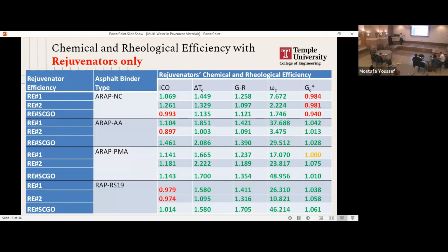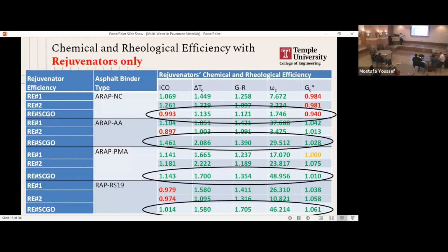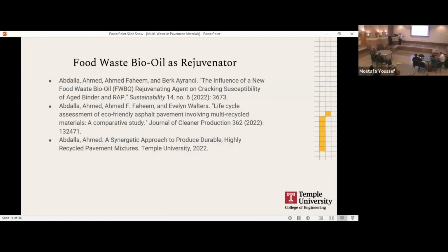These are the different rejuvenators, evaluated through changes in fundamental rheological properties, frequency, crossover modulus, through the improvement in thermal relaxation with the delta Tc, through even improvement in the chemistry with the FTIR measurement. And again, that work has been published.